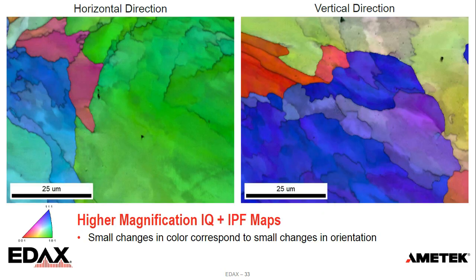In my work, I was starting to look, it's still in progress, at the structure at higher spatial resolutions. So here we're looking at an area where we can see within some of the grains that the color changes. There's small changes within a primary color, and that represents small changes in the misorientation.